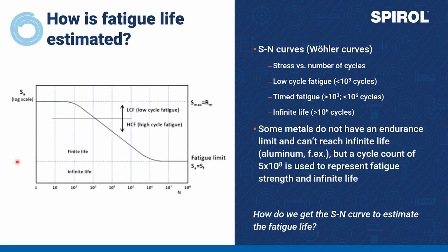Essentially, you can either take the stress in the application and find out just how many cycles it is going to last, or take your desired number of cycles and determine the maximum dynamic stress that would be permissible for that life. And as you can see on the chart, the curve typically has 3 sections: low cycle fatigue, timed fatigue, and infinite life. Low cycle fatigue is considered to be less than 1,000 cycles.